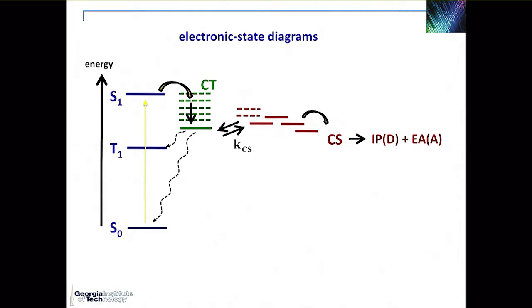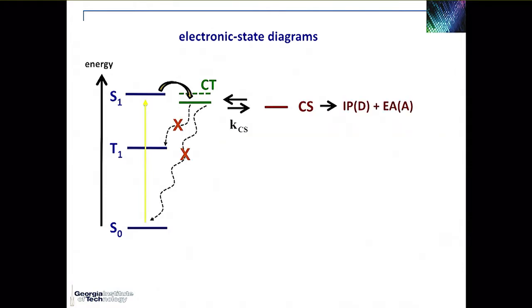And so if I go back to my electronic state diagram, instead of that simple sketch that I had before, we need to try to design the systems, the two components and their interfaces, in such a way that we minimize the width of the CT energy distribution. We need to have the lower CT state very close to the S1 state, and then we need to prevent from those CT states the non-radiative recombination pathways from singlet CT states down to the ground state and from triplet CT states down to the triplet states, for instance, of the polymer.